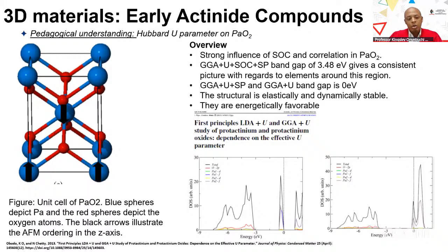But the consequence of what I was doing in my PhD was we were trying to get a pedagogical understanding of protactinium dioxide. And sometimes people ask me, why this system? It was part of the fact that South Africa was interested then in pebble bed reactors. So we were like, okay, can we actually work on thorium and this group of elements and understand this fundamentally? Using the existing theory then, we were not able to properly describe the system. So we applied different theories. And if you look here, we evaluated this material and we found that it's elastically stable, it's dynamically stable. If I go back to my previous slide, I showed you what dynamic stability is, thinking about this in terms of the phonon frequency, and with no negative phonon modes, this is dynamically stable and is also energetically stable.